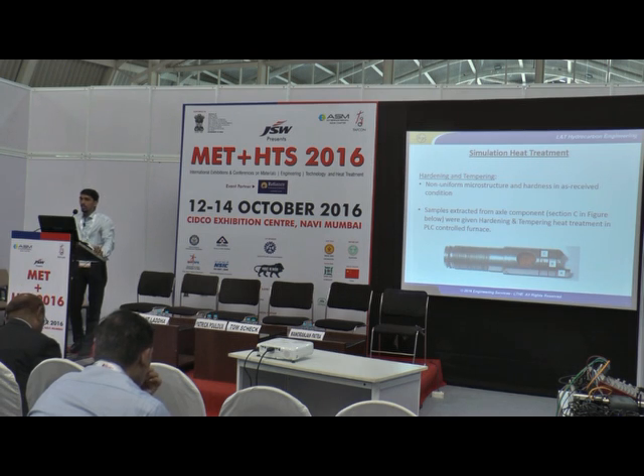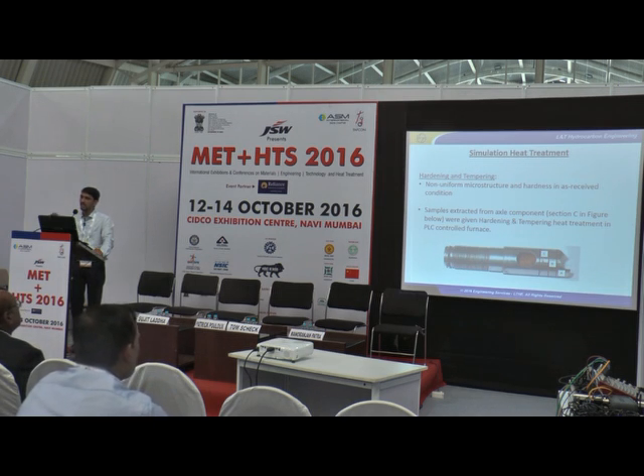Now, what made us simulate the heat treatment of the component in the lab? The non-uniform microstructure gave the hint that something was wrong with the heat treatment of the component, and we tried to simulate the heat treatment in our laboratory to just reconfirm it. So we extracted a few samples from the component, as seen in the image, and provided them with hardening and tempering heat treatment as specified by the client. The temperature and the time specifications were of course there in the client documents.